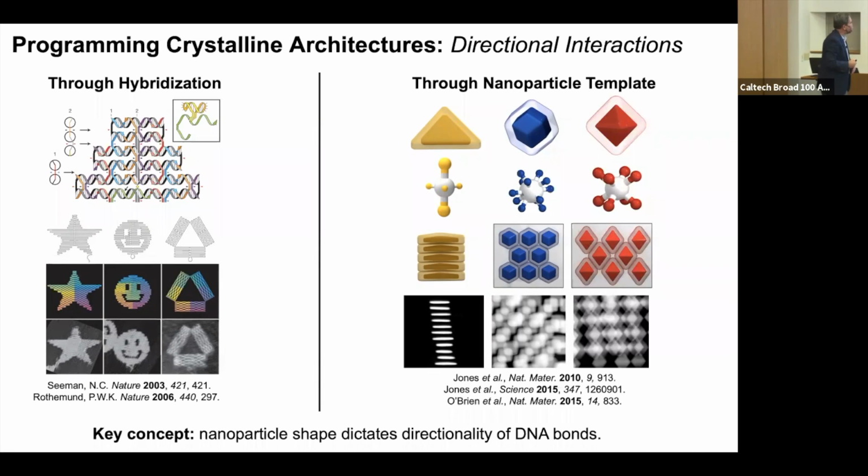The second is, and over here, this is really about using DNA as a smart glue, effectively, to build a structure that's primarily made of what we're calling the atom-based building blocks, the non-DNA-based building blocks. But the second is really important, and that is how we get to valency. So valency over here is achieved by creating rigid subunits through crossover type reactions that take squishy and flexible oligonucleotides, bring them together to form subunits that are rigid that then direct subsequent bonding events.